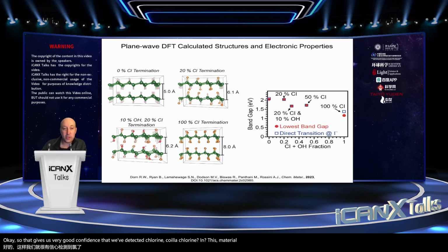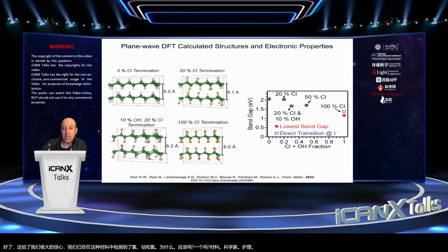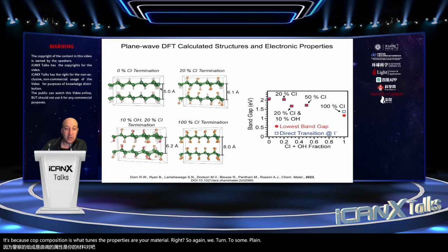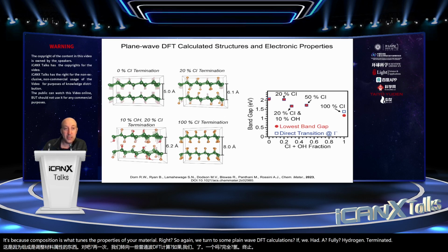Now, why should a material scientist care? It's because composition is what tunes the properties of your material, right? So again, we turn to some plane wave DFT calculations. If we had a fully hydrogen-terminated 2D sheet, you'd see that you'd end up with a band gap that's a little bit bigger than 2 eV.